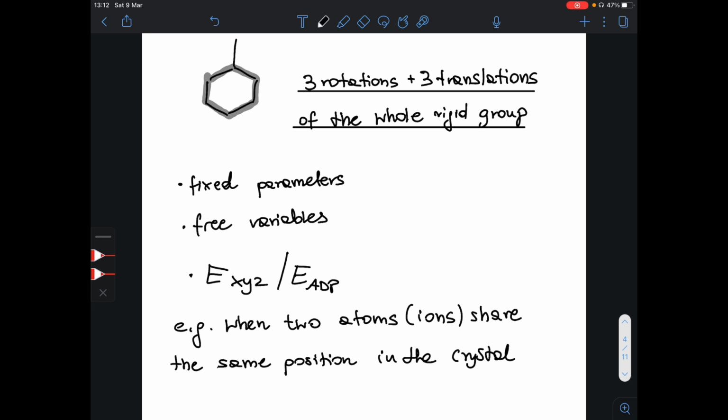And apparently, the lithium atoms are partially substituted in one crystal by sodium cations. So during refinement, if you use the EXYZ constraint, you basically constrain the positions of sodium and lithium to be exactly the same, to model the disorder in a way that the two different ions occupy exactly the same space, they have the same coordinates in your structure, but one of them is, let's say, more rich in lithium than in sodium.